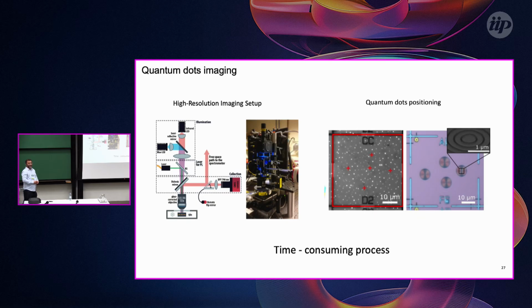But the problem of this kind of approach is that it's very time-consuming, because when you grow this gallium arsenide quantum dot, it's a self-assembly process, and you need to map where the quantum dots are before making the bullseye ring structures. For doing this, we need a high resolution setup. Basically, you take a blue LED and a CMOS camera, you shine the quantum dots at low temperature with the blue LED, and you capture how the quantum dots emit light.